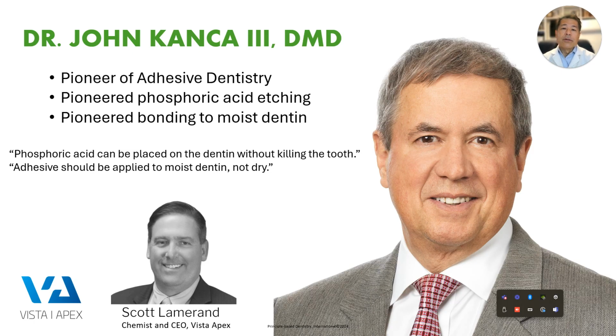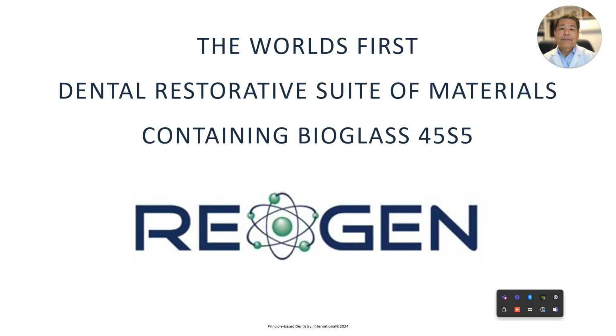So then the manufacturer of that material came back and said, okay, I tell you what, go ahead and place your adhesive. So now we had an adhesion layer, and then place this bioactive material, which was fine. It was better than what we were doing before. But now we're placing this bioactive restorative material into the tooth, but the bioactivity of that material could not benefit all the deeper parts of the tooth where the tubules were, because we had sealed them up with our conventional adhesive. So we had a conventional adhesive that would seal up all the tubules. We'd place this bioactive material on the outside. It would do a better job perhaps at preventing recurrent decay, because now it was bonded. It wasn't loose. It wasn't wiggling around in our preparation, but it wasn't going to help the tooth heal up.